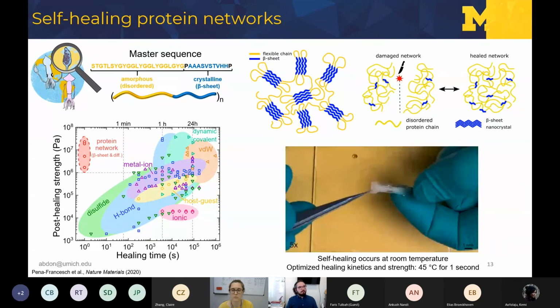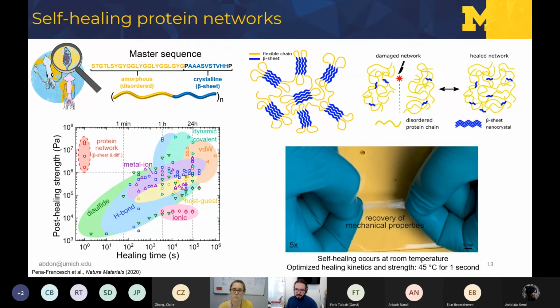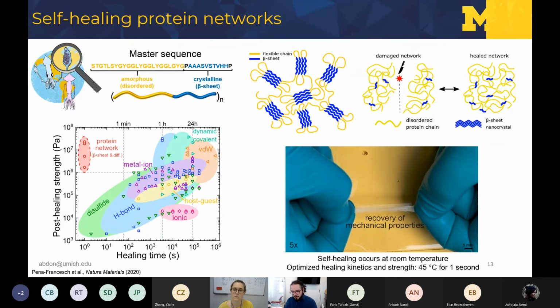And although the healing happens at room temperature and it heals within minutes, we wanted to show that by just giving a little bit of extra help to enhance that chain diffusion, we can have very strong healing in the range of megapascals. I think around 20, 25 megapascals for the most efficient networks that we got. But we can achieve this within 1 second, which is great, because we're in this optimal performance space, right?